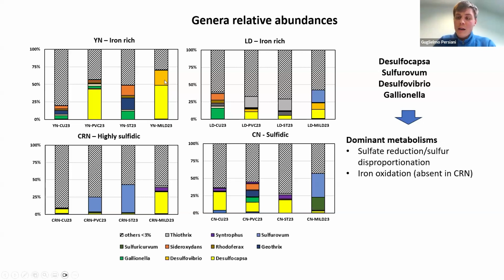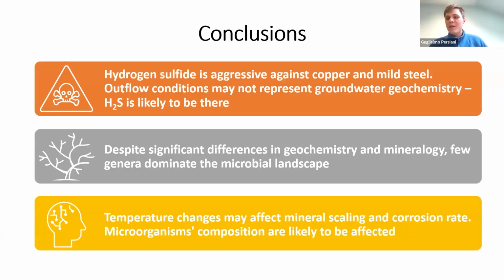And those genera, for example, Desulfocapsa, is a genus related to sulfate reduction and dismutation. So actually this genus produces hydrogen sulfide, and it is common in all the sites, even in the sites where we have high dissolved oxygen and where we have iron. On the other side, we do have microorganisms like Sulfurovum, common in all sites, which oxidize hydrogen sulfide. So they represent common metabolic strategies, and they are common in all the sites, which has been pretty surprising to see. So I know I'm very late, and these are the conclusions.